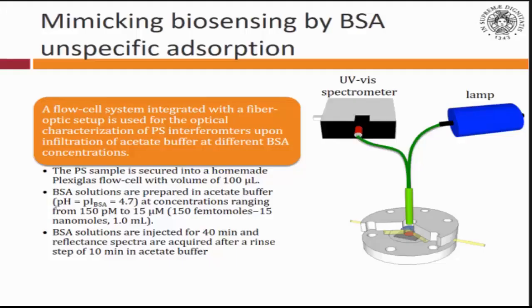It's very simple to probe the optical features of the material. You just put the material into a flow cell, shine white light on it, collect the reflected light into a spectrometer, and get a reflection spectrum. We used a flow cell with a volume of about 100 microliters. As we were new in the field, we decided to first probe BSA non-specific adsorption — this is the best case you can get with a silicon oxide surface, and we are monitoring variation of the refractive index.